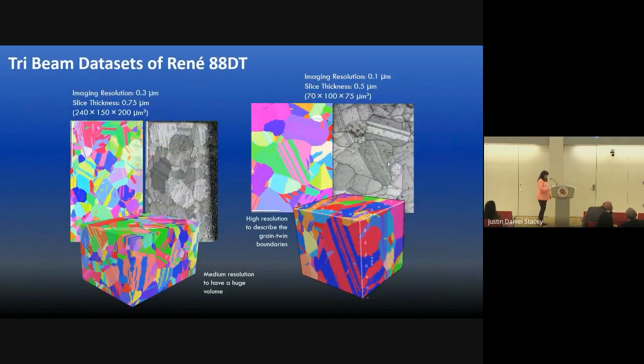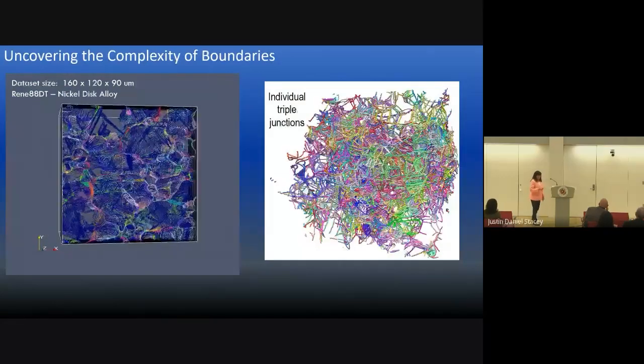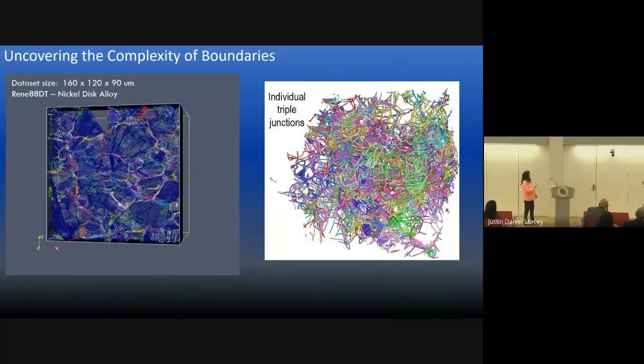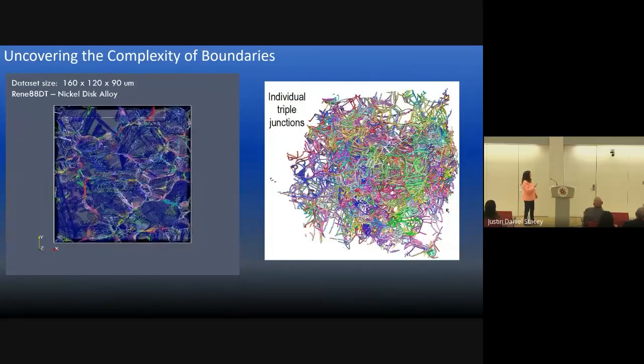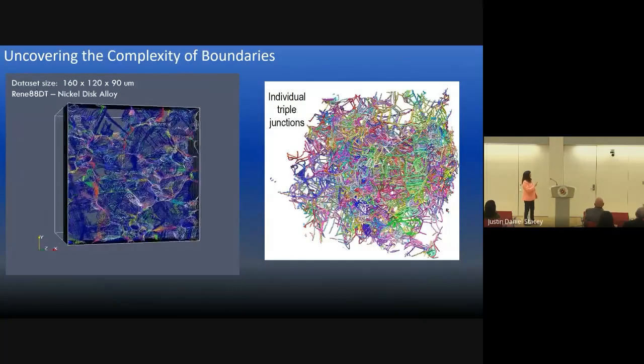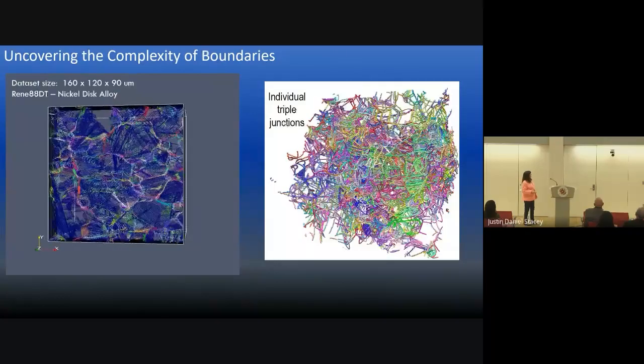And so we've made a number of data sets of these materials at various different resolutions. This is probably the material we have the most data on. And if you look at these red-blue regions, these are grains, but during recrystallization they develop these annealing twins. It turns out they play an important role, and those are the sorts of things that you can image in the system. And so to give you some sense of the population of those special twin boundaries, all the blue ones are the twin boundaries, and all the other colors are regular high-angle boundaries.